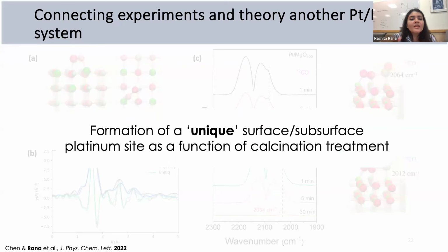So this idea of using a well-defined material, doing experiments on those materials, and then validating that using some computational tool or technique is something that can really help you build on the story and understand how your catalytic site is evolving under reaction conditions. With the help of this work, we were able to identify two different and very unique sites of platinum on magnesium oxide. Magnesium oxide is known to be a very stable support. But in the case of platinum, what we found was that given a specific calcination treatment, you would get different sites of platinum on and in the magnesium lattice.